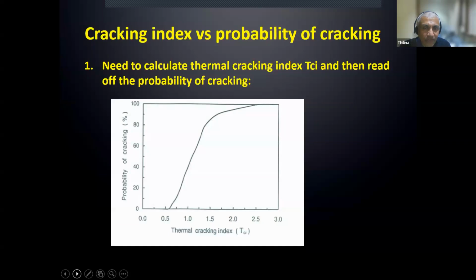Yeah, I was partly involved with developing this. This is a curve we get. What you do at that risk is plot potential thermal stress versus tensile strength on the x-axis, then you look at the probability of cracking. This has been developed from actual measurements over 800 sites, so it's quite handy to use in risk-based assessment. As I understand, even 3 decades ago in Japan, owners needed this curve developed as part of their concreting QA and QC plan.